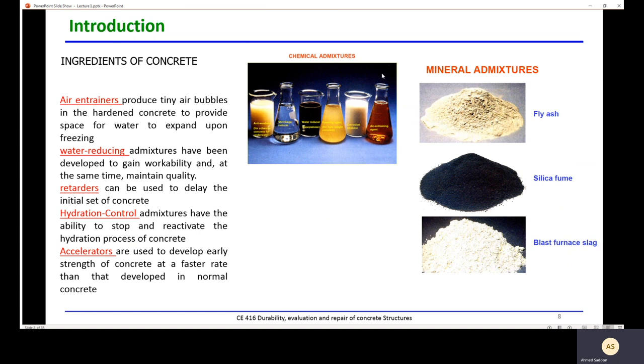Chemical admixtures are very important. One example is air-entraining admixture, used when concrete is exposed to freezing and thawing conditions. It provides spaces within the concrete so that when water inside the pores freezes and expands — since freezing increases water volume — the internal stresses can be accommodated and damage is avoided. Another important chemical admixture is water reducers, the most famous being superplasticizer, used to enhance workability and produce high-strength concrete.